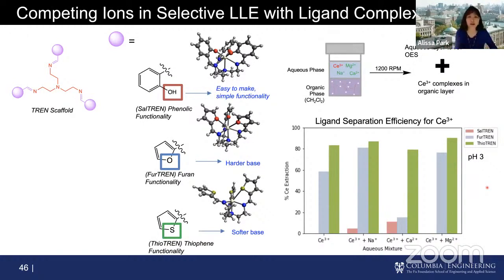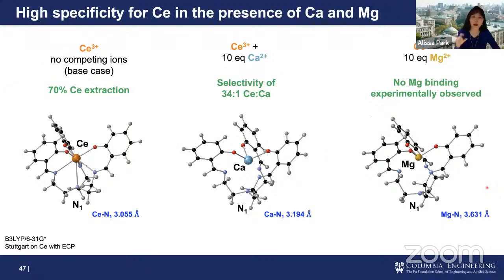This does work. And one of the reasons is that not only was the binding energy strong enough, but as shown in this DFT calculation, cerium sits very snugly in this cavity of structural ligands, connecting to all 7 binding sites. But in the case of calcium and magnesium, they don't get the full binding of all binding sites, so they're kind of dangling. Because of that, we were able to get really selective cerium capture in the presence of calcium and magnesium. And by keeping calcium in the solution, we were able to do carbon mineralization downstream.